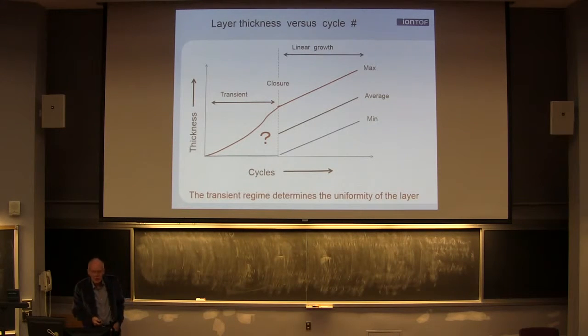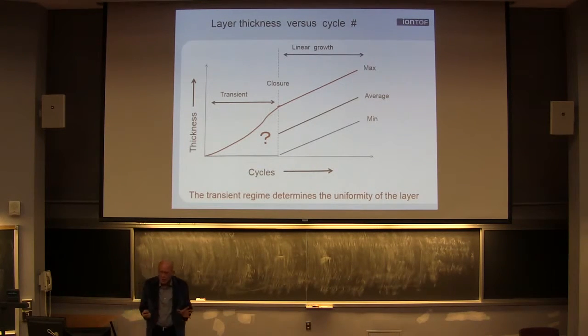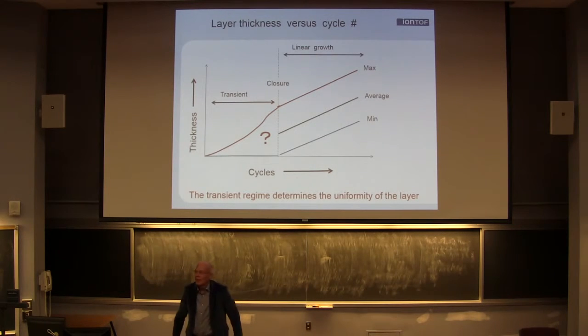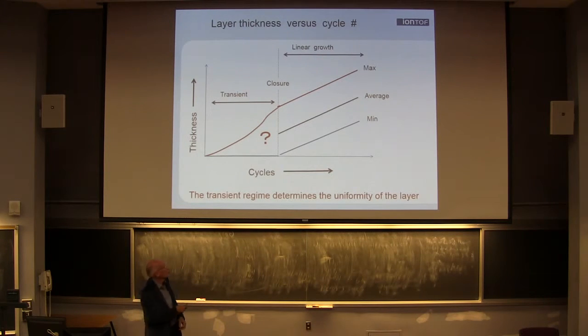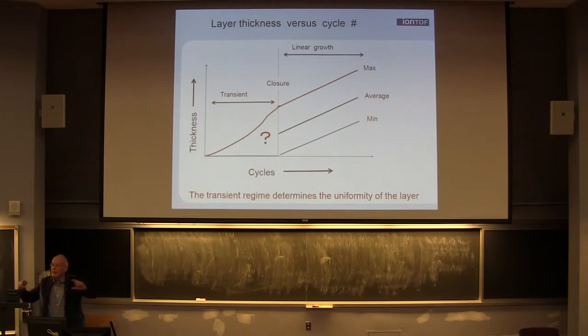Atomic layer deposition. I showed you already a little bit before. It is very important: how do I do cycle-by-cycle growth so that it goes layer by layer, so that it is very homogeneous layers, a uniform thickness. However, if it nucleates at one place, after cycles it starts at some place, it goes out. But there are other places that are still uncovered. And it may take many, many cycles. Sometimes it takes 200 cycles before that layer is closed.